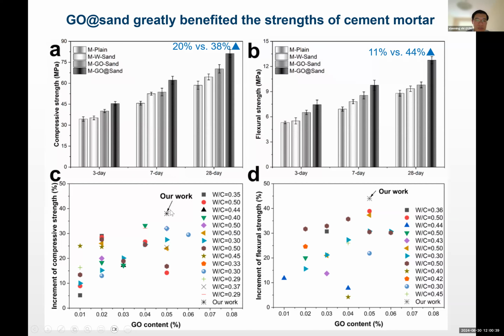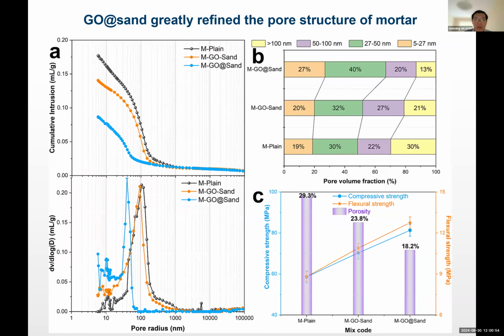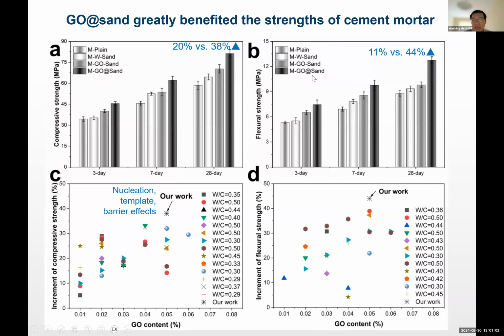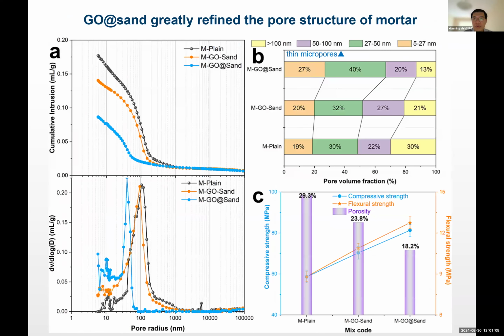So you can see our work is standing out compared to many other studies out there in terms of better improvement in the strength and slightly lower usage of graphene oxide. So again, graphene oxide serves many different roles. Again, we used mercury intrusion porosimetry to understand what happened. Basically, we're seeing more finer pores, and you see improvement in strength and reduction in porosity.